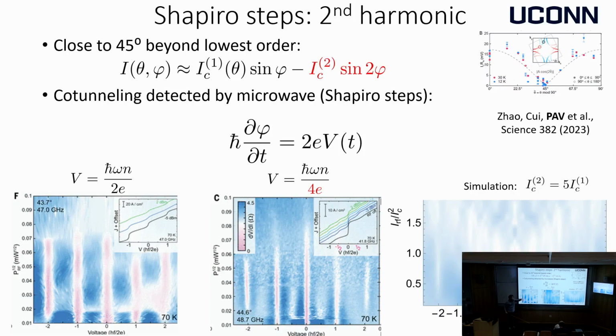And the oscillation here is created by hand. You just send an AC current through your junction, and what happens is that you indeed see pronounced anomalies at the voltage that's equal to integer number of those frequency steps. Now, if you have two Cooper pairs tunneling simultaneously, instead of 2e, you get 4e, so you expect steps also appearing at half integer voltages, and that's indeed what happens for samples that are close enough to 45 degrees. So this one is actually quite a bit closer than this one to 45 degrees.